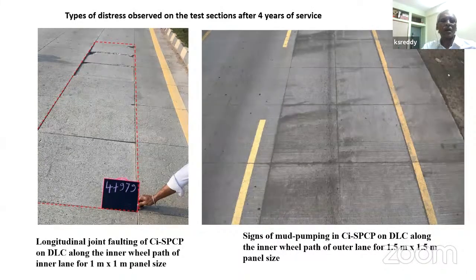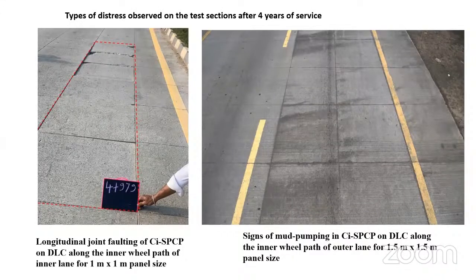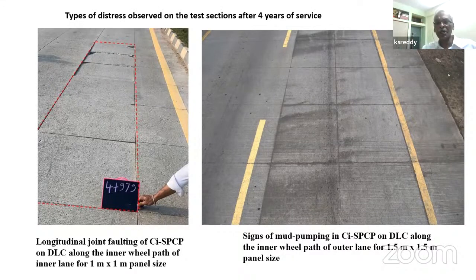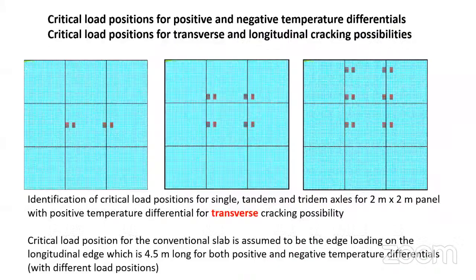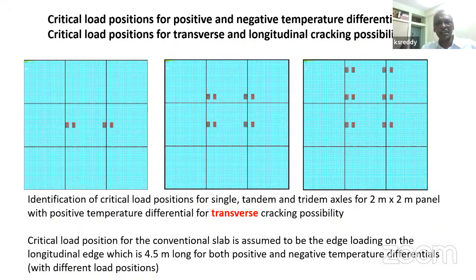We didn't see this on whitetopping pavements, where we place the panel concrete on a dense bituminous macadam layer. So this was the analysis of a panel concrete pavement, where we considered different sizes, different load positions, positive temperature gradient, and negative temperature gradient. Almost 30-40 different combinations of critical load position as well as temperature gradient were examined, both for longitudinal cracking and transverse cracking, top-down as well as bottom-up.